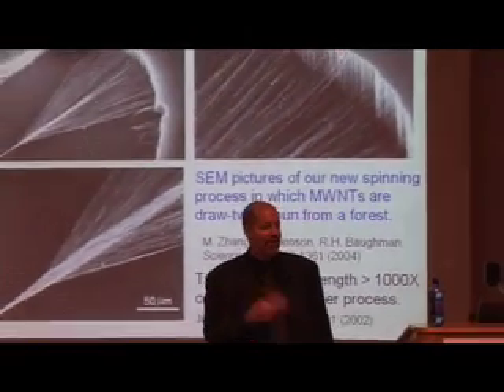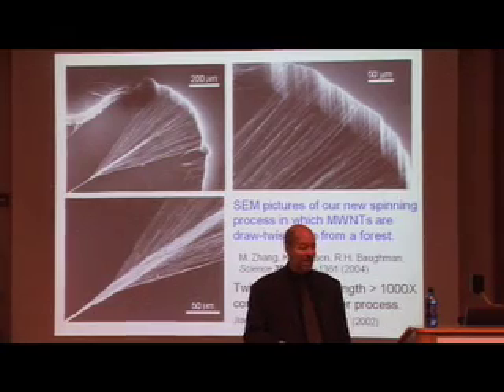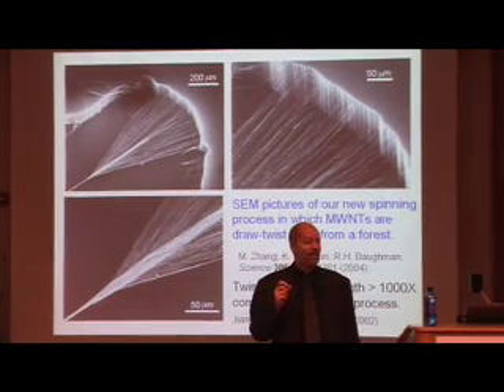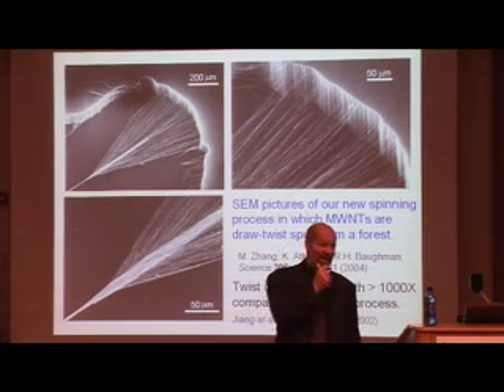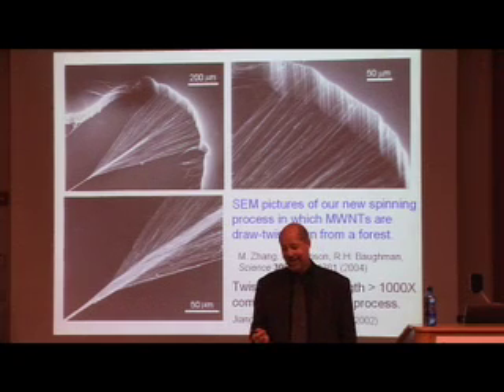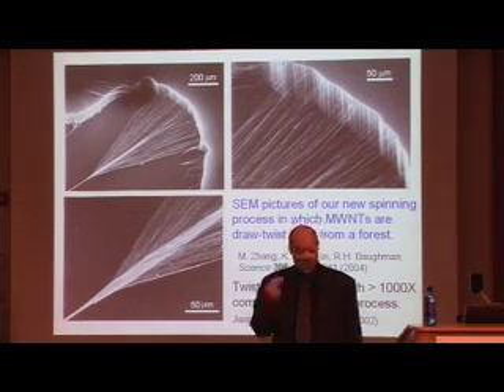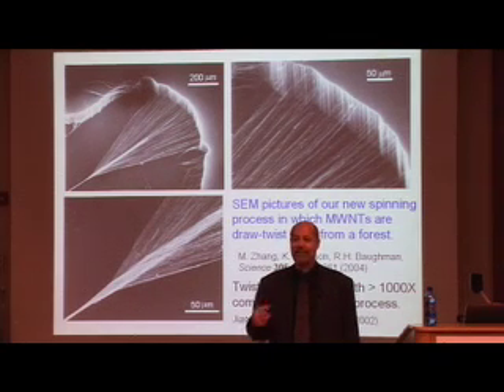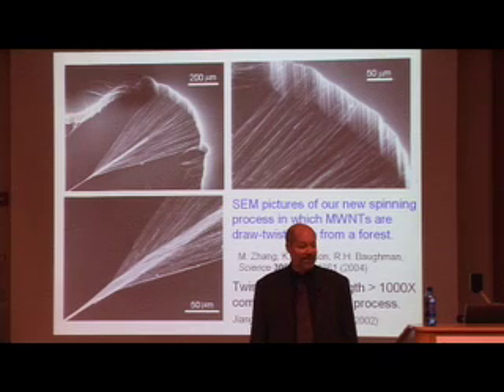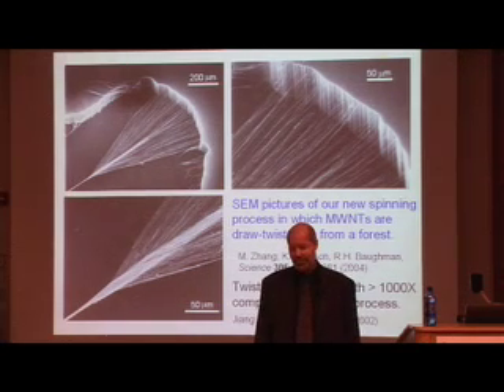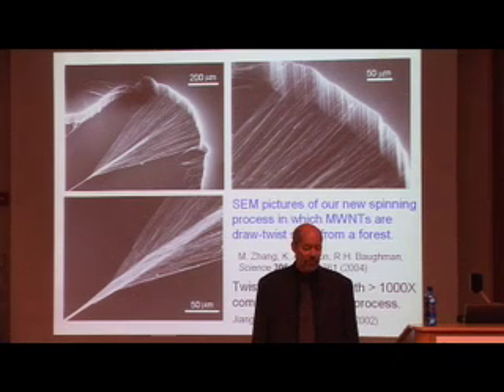We are no longer focusing exclusively on this type of solution-based spinning. Why not? Well, the problem is, if you really want to harvest the extreme mechanical properties, thermal properties, electrical properties of carbon nanotubes, you really want carbon nanotubes which are very, very long, because every time you get to the end of a carbon nanotube, the electron or the phonon has to get to the next carbon nanotube. And that process, the unlikelihood of that process in some cases degrades the overall properties of a yarn and sheet. And you can't process from solution or melt very long carbon nanotubes. It's basically solution or melt processing is limited to short nanotubes.